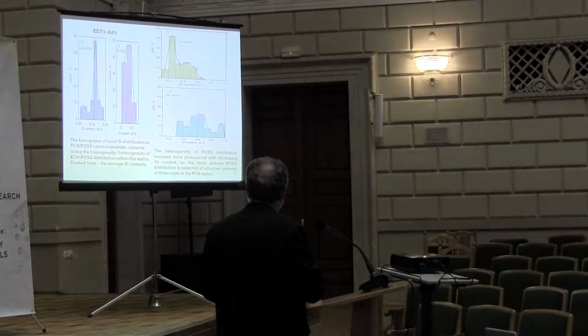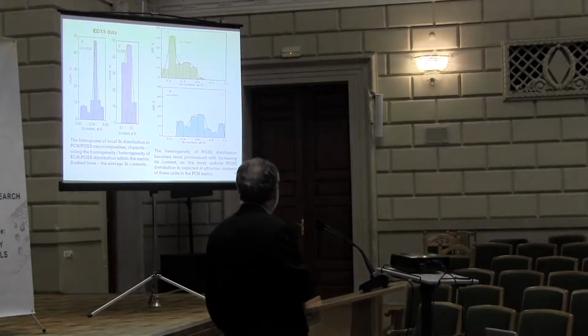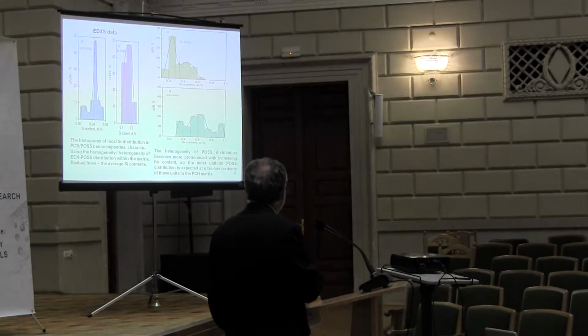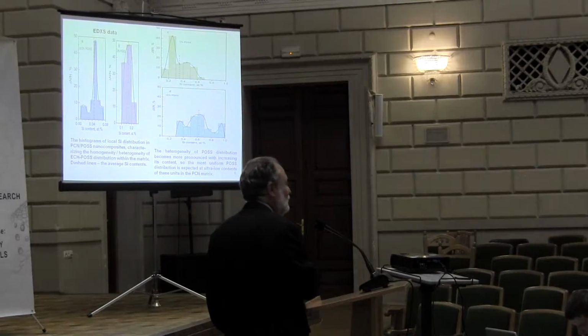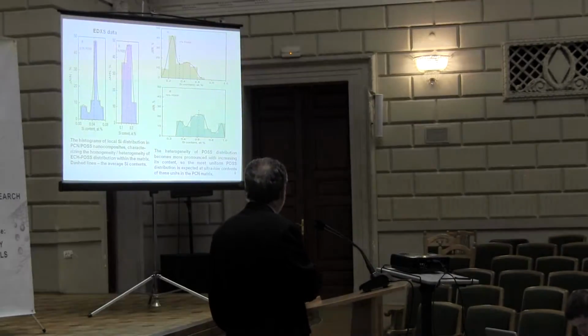And here we have the histograms of local silica distribution in PCM/POSS nanocomposite, characterizing the homogeneity and heterogeneity of the distribution within the matrix. And dashed lines give us the average silica content. So it's for 0.5 and for 2% of course we have quite narrow distributions, good dispersion, and wide distribution for higher content of POSS in the system. So for 5% and for 10% standard.